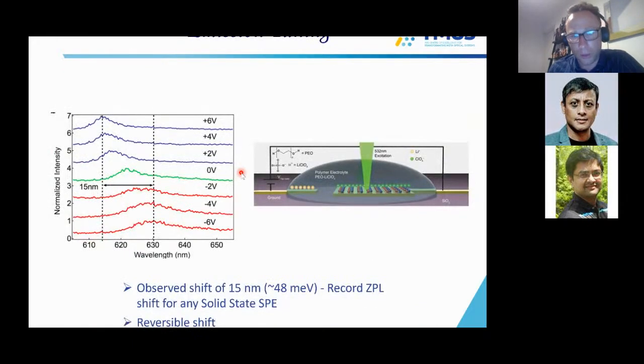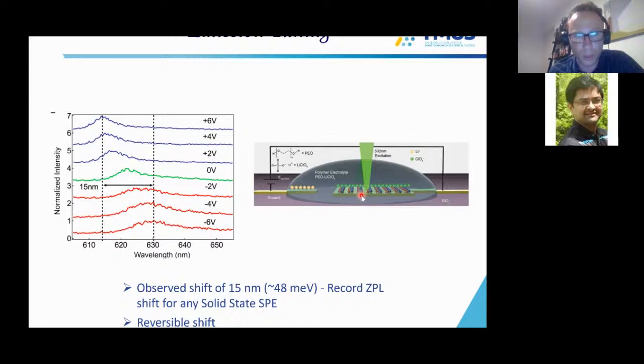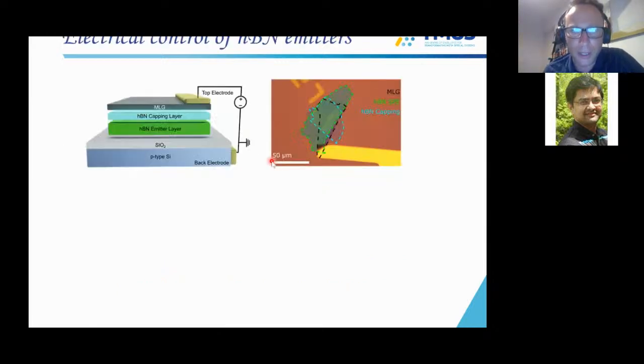Okay, so what can you do with them then? Well, one thing that we did is some tuning, and I showed you already one slide on electrical field tuning and strain tuning. Back in 2019, already 3 years back, we also put electrolyte on top of this hBN because it's a 2D material and we can shift it. But what we did recently is try to really dry up the system and to do things electrically. And the results were actually quite surprising.